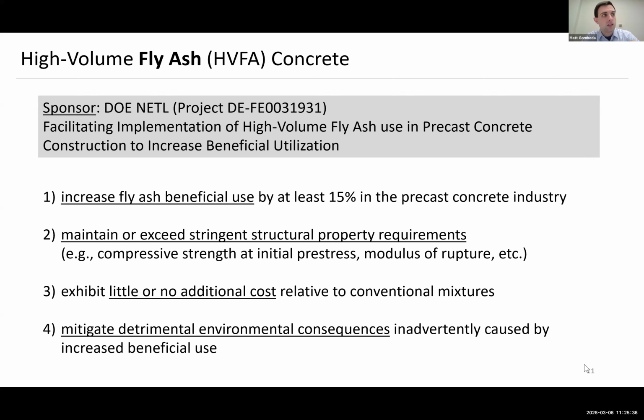And the reason that there's been limitations for having higher uses of fly ash or other SCMs is because we really are sometimes at a disadvantage with early age strength gains when we have materials that have lower heats of hydration. So there's been a cap, like about 25% for many years of fly ash because they were worried that you couldn't get the higher early strengths if you went higher dosage of fly ash.